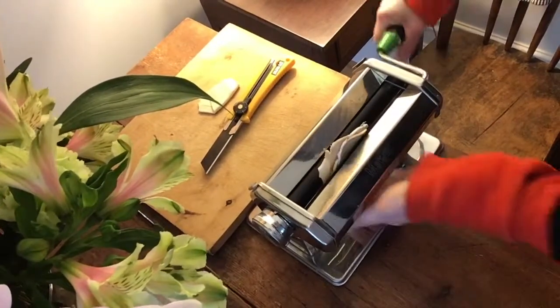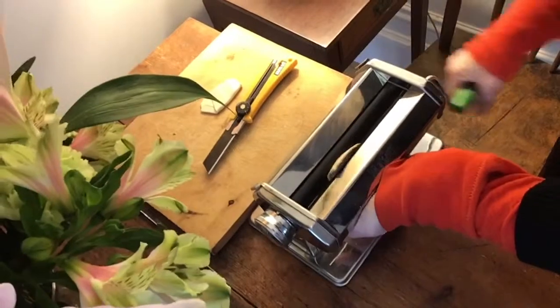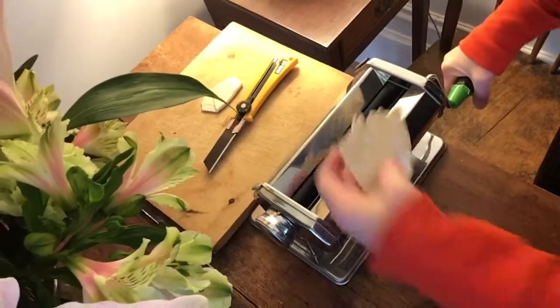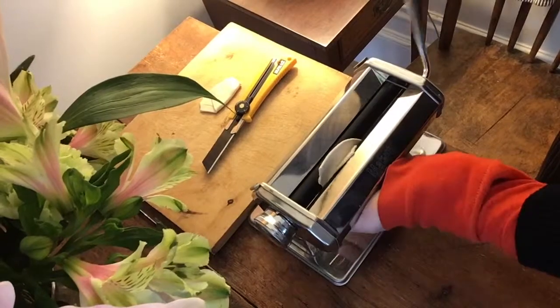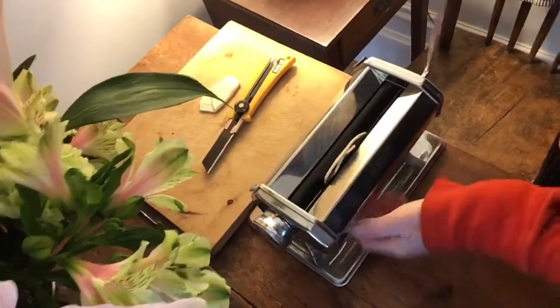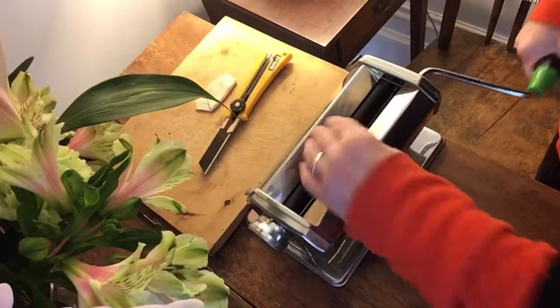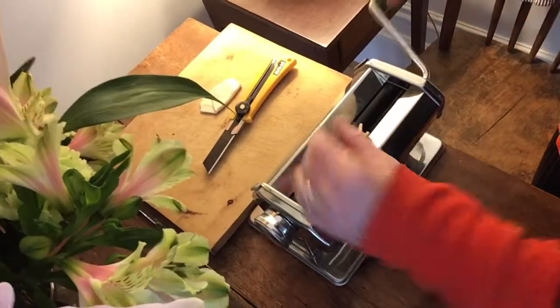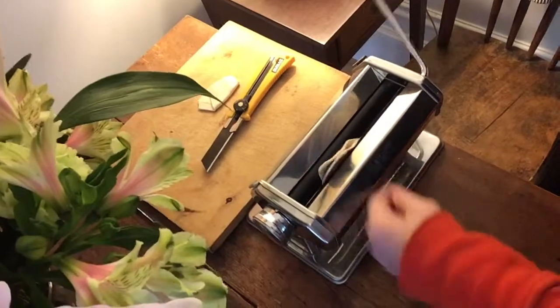You can see how I'm feeding this down through, folding it, and putting it back through. When the polymer's fresh, this is really easy. When it's not so fresh, sometimes it'll crumble, and that's when I usually warm it up a little bit next to my skin in a plastic bag — some way to get a little more heat into the polymer. You'll find it mixes more easily when it's warm. We're going to put it through the pasta machine repeatedly until the colors are blended into what I call the neutral clay. If there's a number — a magic number — it's 30. Thirty times through the machine is a good number to know you're conditioning the clay properly and getting the most elasticity. Within 30 times, you should have a nice smooth mix of clay.